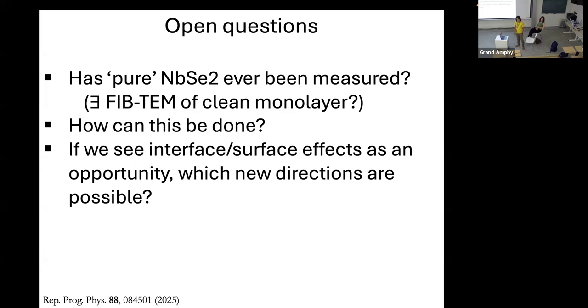And the third point about this charge density wave: I do not remember it exactly, but I think there was a paper on ARPES around 2012, the first author was Borisenko, where they showed the existence of a pseudogap in the charge density wave state at temperatures way above the charge density wave temperature of 33 Kelvin. So I do not know if it is monolayer that is amplified and one sees the charge density wave at high temperatures. But there was an ARPES paper which found remnants of the CDW way above the TC of CDW in NbSe2. So how do you interpret that?